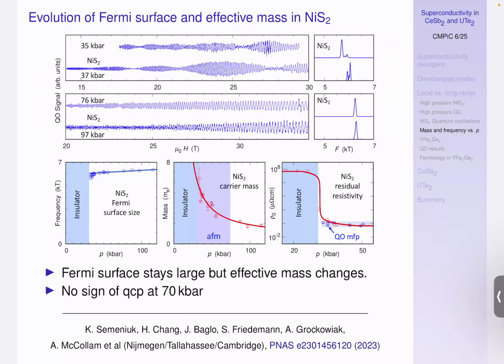Now, when you track these oscillations as a function of pressure, we went from about 35 kilobar, which is roughly where it first becomes metallic, all the way to about 100 kilobar. And you can see the frequency of oscillations and also the mass. So the frequency doesn't change very much. It's almost constant. It just changes a little, which is exactly what you would expect when you compress a solid, because the atoms come closer together. So the Brillouin zone expands and the Fermi surface expands with it. It's actually almost exactly that effect.